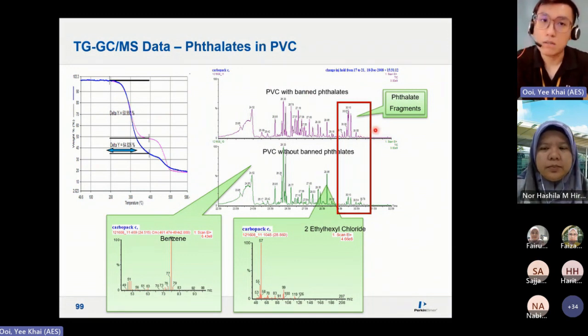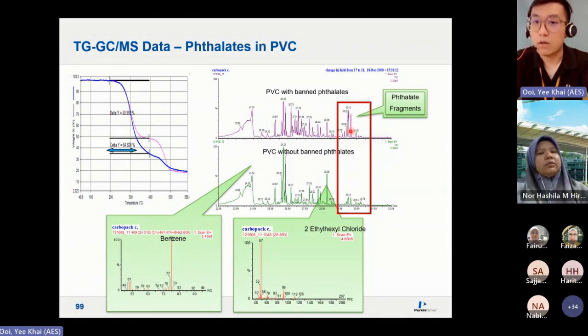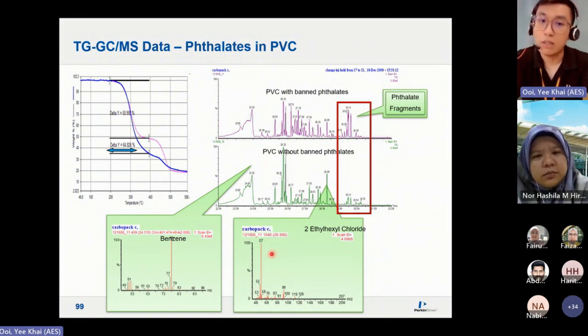From the GCMS data, the chromatogram data, you can obviously see that the one without banned phthalates has a much lower concentration, because peak area indicates how high your concentration is, or the component of it. For the banned phthalate, it is much higher. So now we want to know what the banned phthalate is. Taking this retention time, we check with the MS library, the NIST library. It tells us there's a benzene and also 2-ethyl hexyl chloride. Now this is actually DEHP, a plasticizer, the phthalate that's been added for PVC processing.